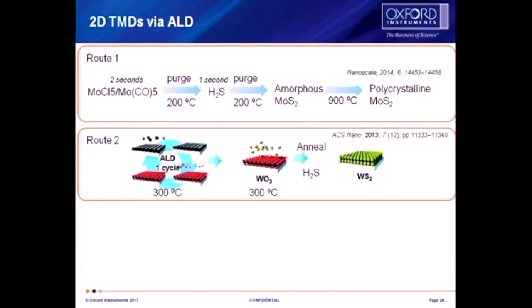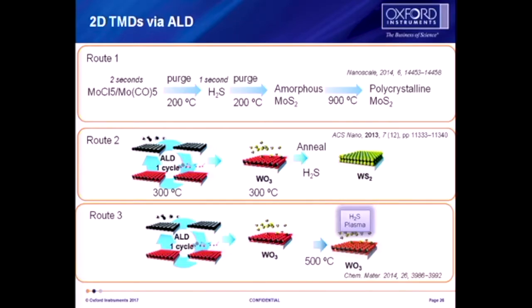The second way is with tungsten sulfide. You could deposit a single layer of tungsten oxide, and then do an anneal to replace the oxygen with sulfur. Again, a reasonable way of doing it. The third route is to expose it to a plasma at the end at 500 degrees C. Again, it's still fairly high temperature.